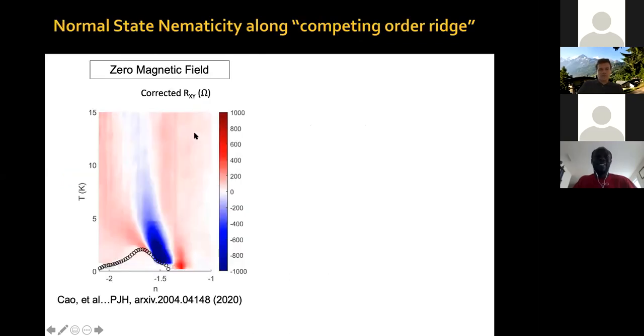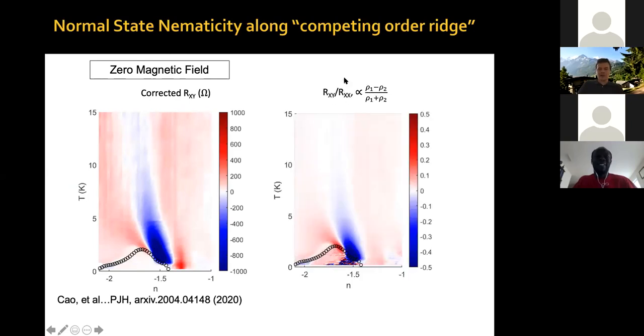Okay, so this measurement at zero magnetic field, where now I have even corrected for small misalignments between the electrodes and all kinds of geometric factors to make sure we do as careful an estimate of RXY as possible. You can see that it indeed shows this region of high anisotropy. You can even normalize by RXX so that you get a full sense of how strong the anisotropy is. And this anisotropy is of order 50% in this region. So it's a very strong anisotropy. It's not a weak effect.